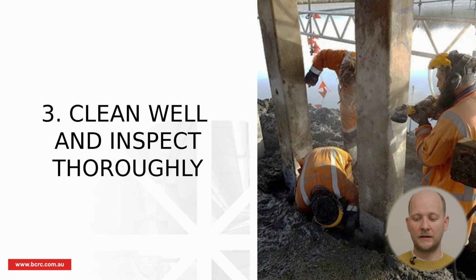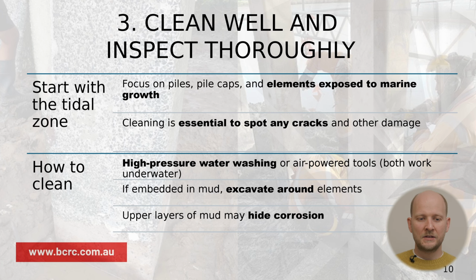Clean well, inspect thoroughly. So start with the tidal zone. Focus on piles, pile caps and other elements exposed to marine growth. Without proper cleaning, it's very easy to miss, I'd say, about 70% of the cracks and deterioration and other damage. How to clean?